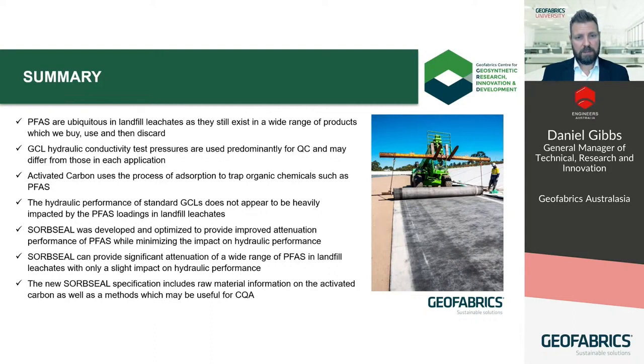We then explored the development of SORBSEAL and the ability to optimize the product for site-specific challenges using different raw materials. We saw that SORBSEAL can trap a wide range of PFAS in landfill leachates, which also contain a number of competing co-contaminants, over and above the standard Alka-Seal GCL, with only a minor impact on the hydraulic conductivity. And finally, we reviewed the new SORBSEAL specification, which lists a couple of the key raw material properties of the activated carbon, in addition to some of the methods which can be carried out by independent labs for CQA purposes.